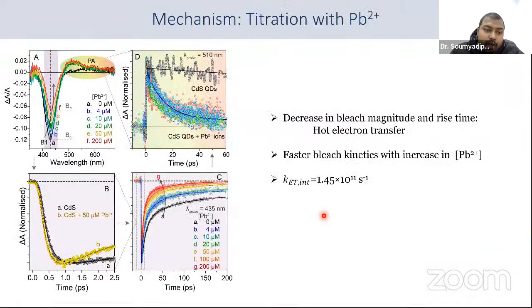So what we did, we again did the TA. The TA measurement shows that with increase in the lead concentration, the bleach signal decreases. This is the bleach signal. All these bleach signals, in presence of lead 2+, are at 1 picosecond delay. The black one is without lead 2+, and with lead 2+, the bleach decrease is prominent. Why the decrease in the bleach signal?